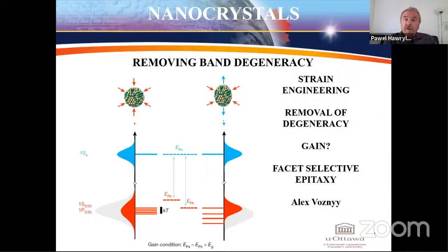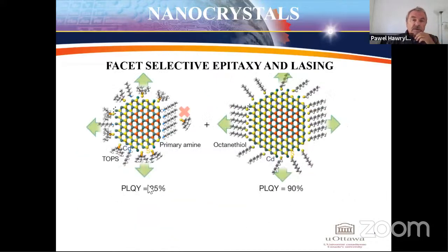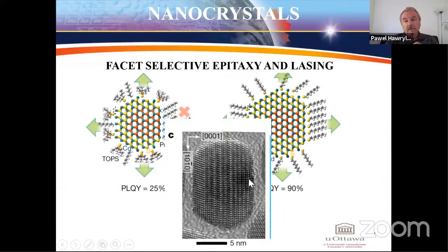So this is accomplished by strain engineering, and the strain engineering proceeds through facet selective epitaxy, and here my colleague Alex Voznyy has been essential in doing this. So this is an example of such a non-symmetrical crystal through the facet selective epitaxy, and also a problem of passivation of such a nanocrystal has been resolved, so that in the end a very high quantum yield with an isotropic nanocrystal was achieved, and here is a structure of such a nanocrystal.